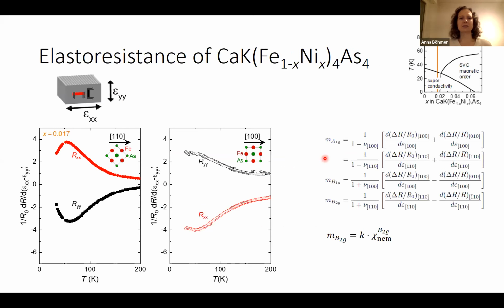Elastoresistance I don't need to introduce anymore, thanks to the previous two talks. And we opted to measure two different crystals that are mounted perpendicularly to each other on a piezo stack and a pair of crystals for each crystallographic direction. So here I showed the longitudinal and transverse elastoresistance for one specific composition as an example. From this data, you see, well, the coefficients are fairly small. There's this sign change between longitudinal and transverse, another one between the two crystallographic directions.